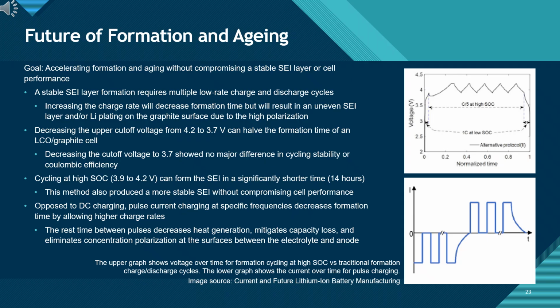Promising strategies include lowering the upper cutoff voltage from 4.2 V to 3.7 V, which can reduce formation time for LCO/graphite cells without compromising cycling stability. Another method is conducting formation at high SOC, 3.9 to 4.2 V, which enables SEI formation in about 14 hours while maintaining performance. Pulse current formation is also gaining traction. By alternating brief high-rate charging with rest periods, heat generation and polarization are reduced, allowing faster SEI development with minimal degradation. Overall, these methods focus on accelerating formation time while ensuring a high-quality SEI layer that supports long-term safety and cycle life.